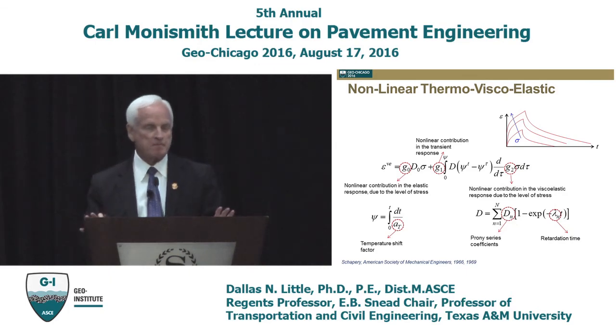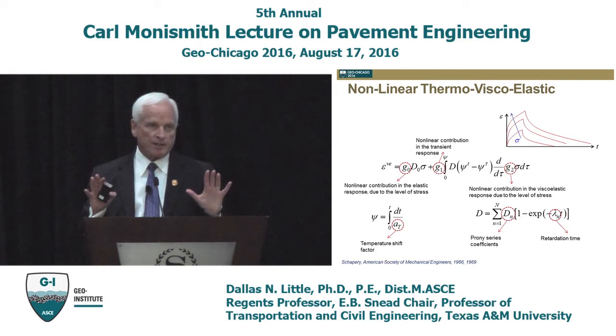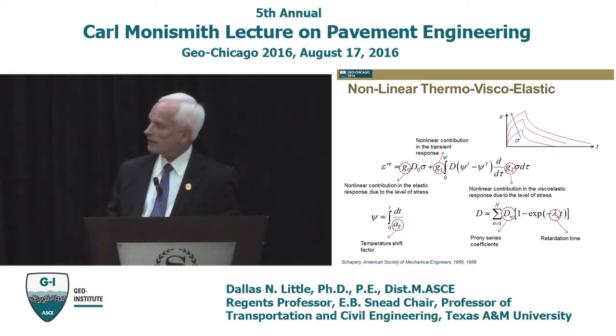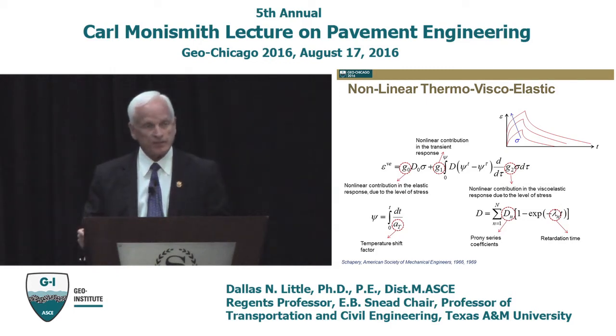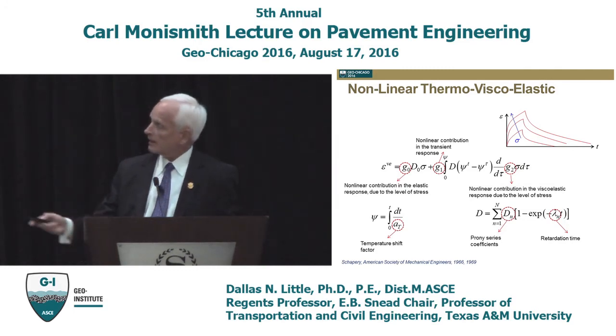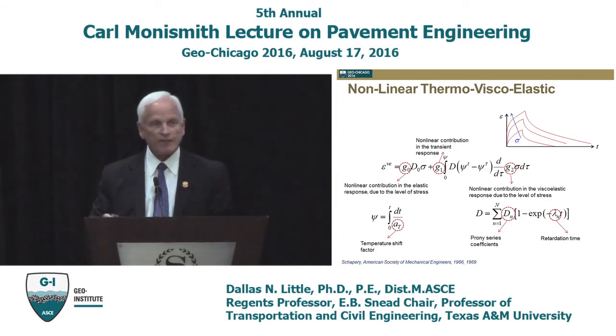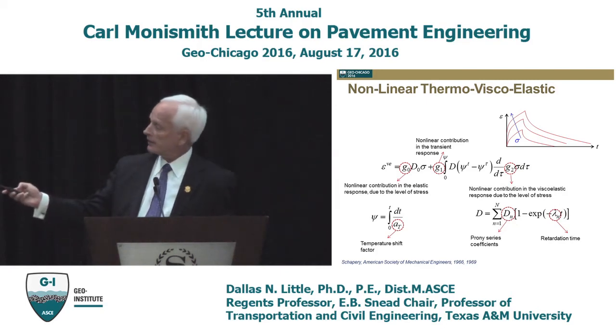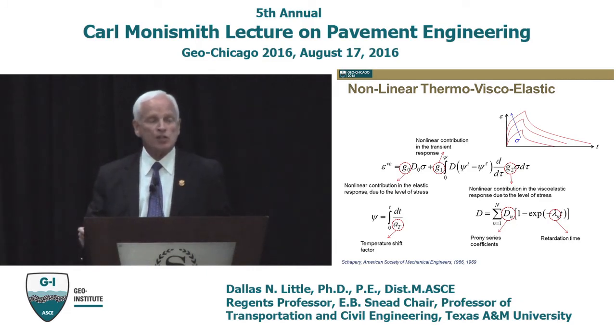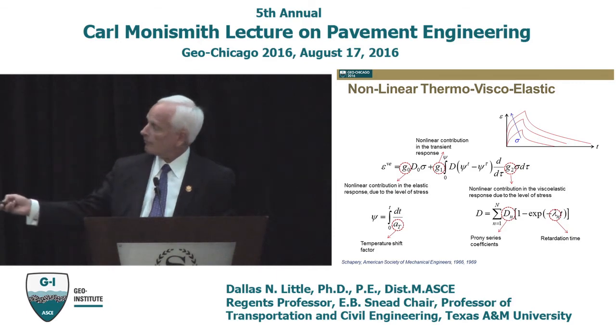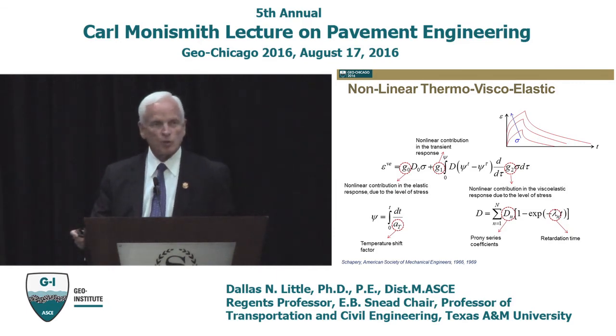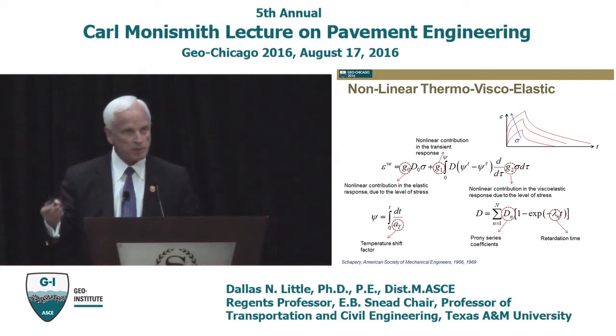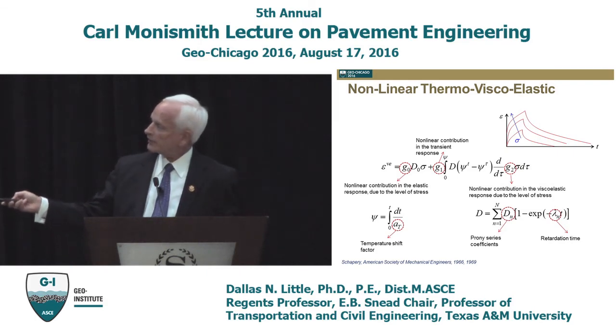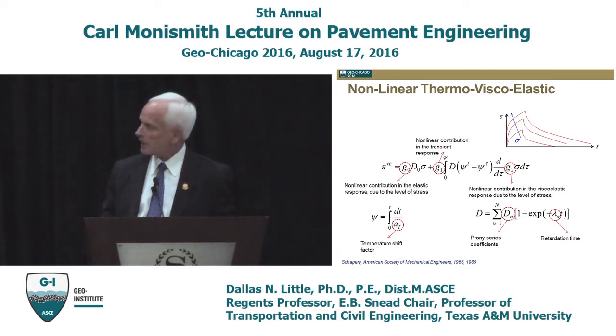So our model, Panda, is a nonlinear model, and it characterizes the asphalt as nonlinear, viscoelastic, viscoplastic. The model that we use for the nonlinear viscoelastic portion is a model that was developed in the late 60s by Dick Schapery at Texas A&M. And the G terms in this particular model define the level of the stress sensitivity that makes it nonlinear. The first, G sub naught, modifies the initial compliance, the elastic response. The terms just before and after the integral, G1 and G2, modify the transient compliance response. And of course, we have a time temperature shift factor involved in this calculation of the viscoelastic properties.